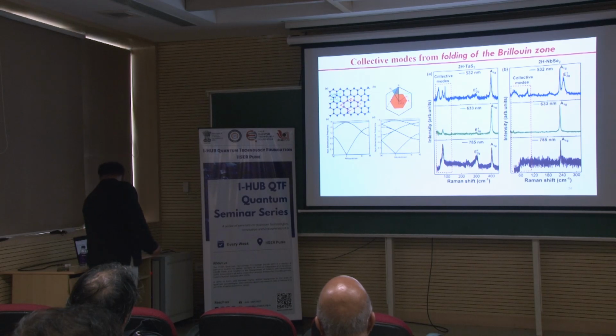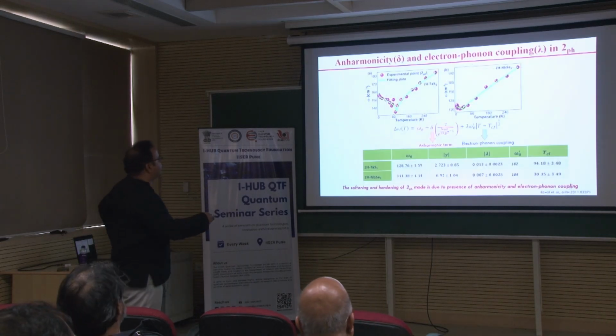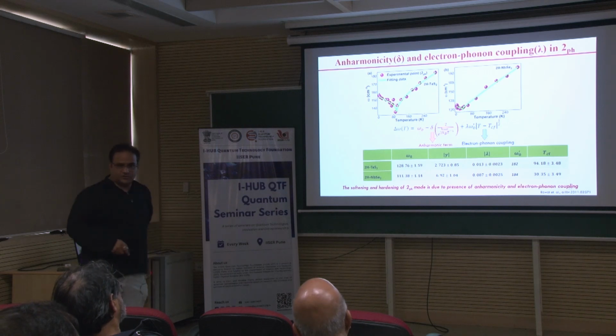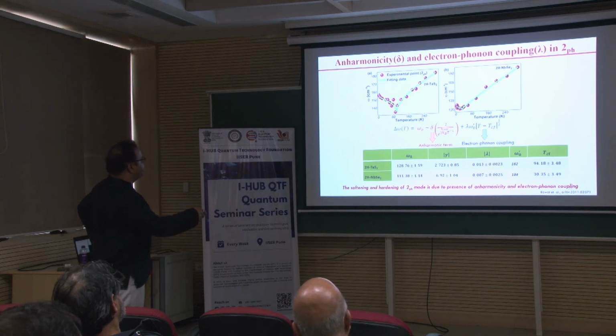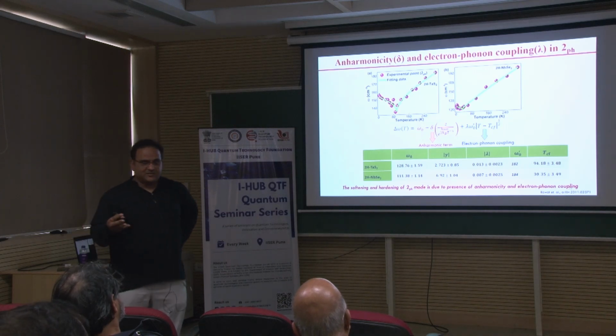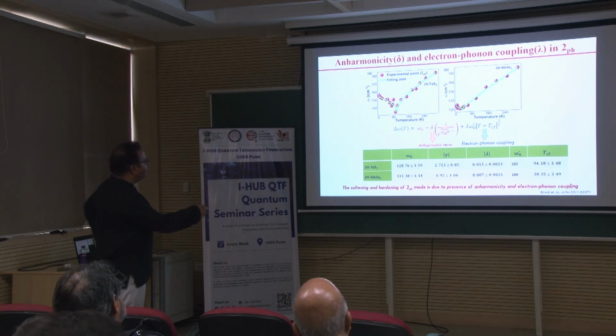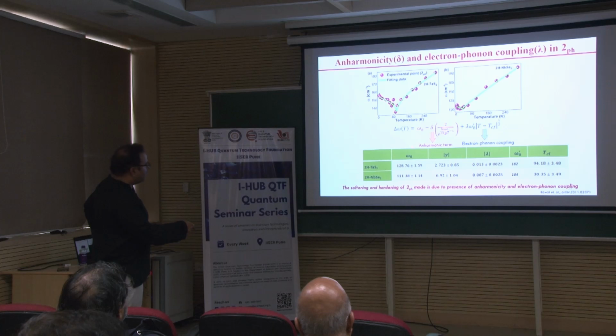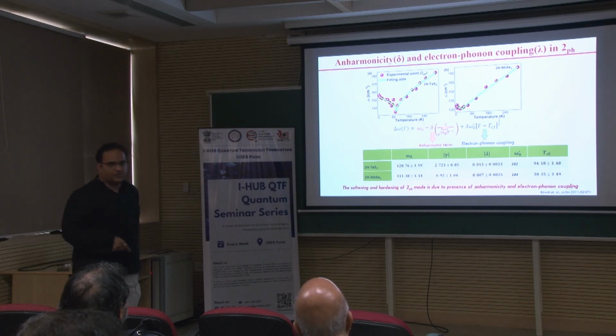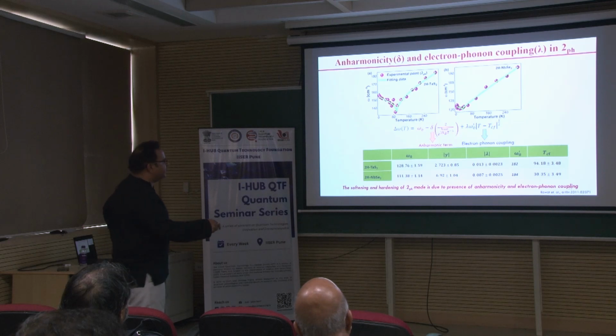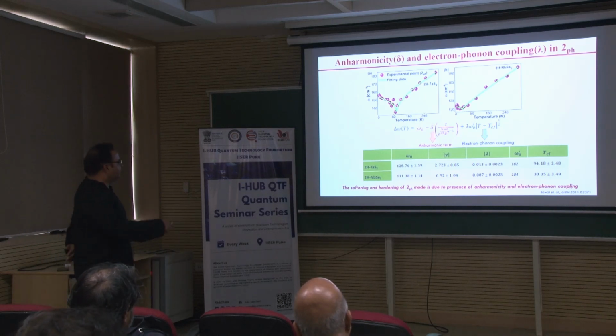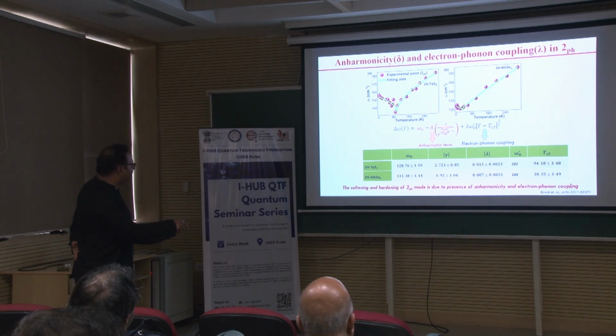We also estimated, if we look at the temperature dependence of the 2pH mode, from higher temperature you go down and it goes up again. If I go from low temperature to high temperature, we call it softening. From here to here, if I go with the temperature, I call it hardening. This is there in both, and by fitting these equations we can estimate how much is the anharmonicity in the sample, and at the same time how much is the electron phonon coupling constant in these materials. If you look at here, the delta value represents the anharmonic term.